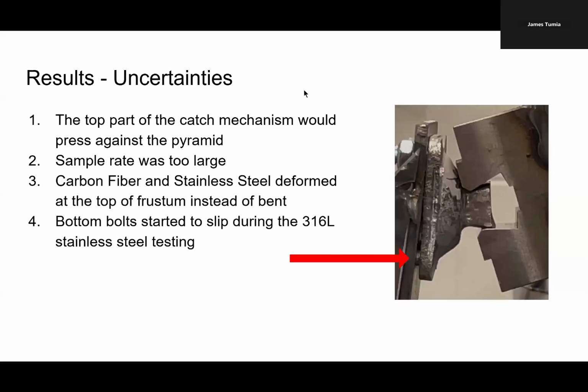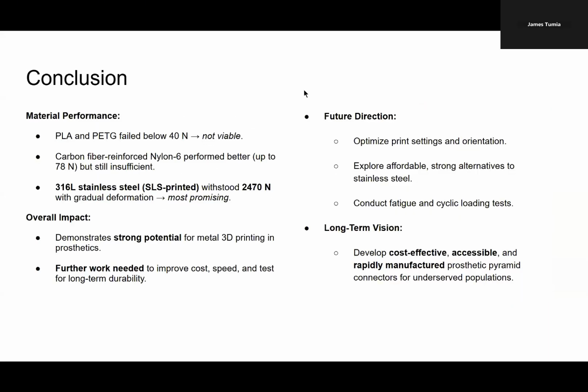To conclude, our testing revealed some clear and important differences in performance between materials and print orientations. PLA and PETG, while inexpensive and easy to work with, failed at relatively low forces, under 40 newtons, which makes them unreliable for real-world prosthetic applications. The carbon fiber reinforced nylon 6 performed better, managing up to 78 newtons, but still fell well short of the strength needed for load-bearing components in a prosthetic limb.